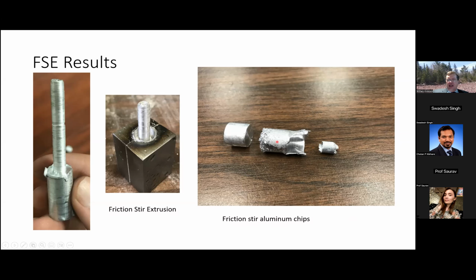You can see that down here at the end of the chips, they fused, but they have not solidified to a solid workpiece. Down here, within these two regions, there was chip solidification, and this is just a backer block that was used to make sure that we did not crash into the insert.